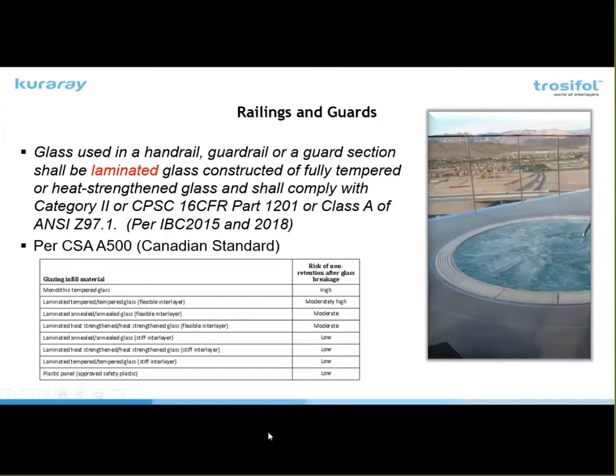Now, in the Canadian standard, CSA A500, which came out in 2016, they have a table in there that talks about the risk of non-retention after glass breakage. And you can see with tempered glass, it's a high risk. When you get a flexible interlayer like a standard PVB, you can see it only goes to a moderately high or moderate risk, and you'll see why in a minute. When you get a stiff interlayer, and the standard defines a stiff interlayer as something with a Young's modulus of over 300 megapascals, so, you know, a SentryGlass would fit into that category, it becomes low risk.